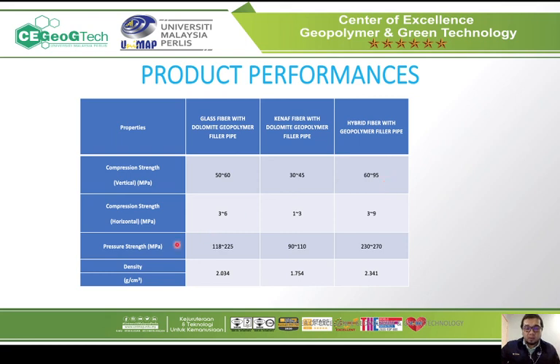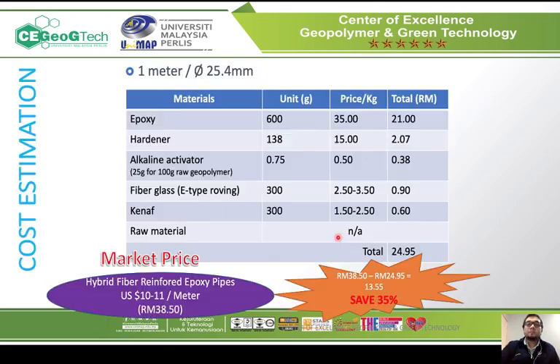So as you can see also, at the pressure strength, the hybrid fiber with geopolymer filler pipe gives the highest pressure strength, around 230 megapascal to 270 megapascal. And then this is the cost estimation to make a 1 meter pipe with 25.4 mm diameter. So for the epoxy, 21 ringgit, hardener 2 ringgit, alkaline activator is around 38 cent, glass fiber 90 cent, kenaf 60 cent, raw material is not included.